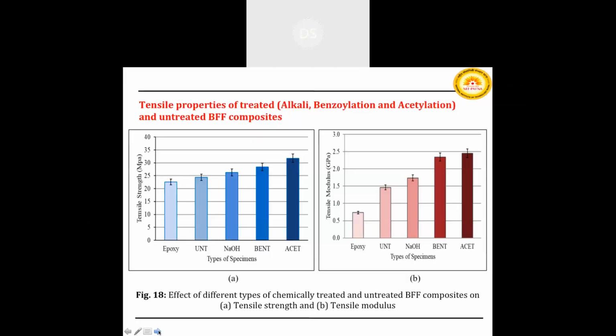Okay. The next slide is tensile properties of treated based on the alkaline treatment, benzoyl or acetylene treated or untreated Borassus fruit fiber composite. In this graph, it shows the tensile strength has been increased by approx 7 to 8% in case of NaOH treated, 16% in case of benzene treated and 30% in case of acetylene treated based composite when compared to the untreated. Similarly, the tensile modulus has also been increased by 18% in case of NaOH treated, 60% in case of benzene treated and 67% in case of the acetylene treated based composite as compared to the untreated Borassus fruit fiber composite.